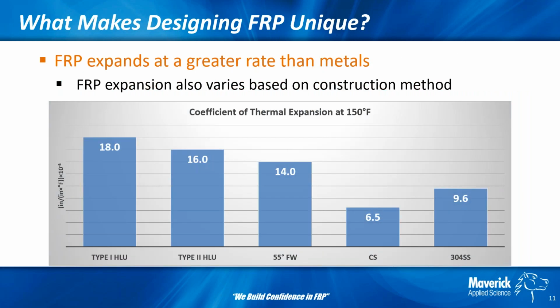Thermal expansion. This is a very big deal for FRP compared with steel. The bar on the left is for type 1. So the resin is what expands, so you'd expect type 1, most resin content, to expand the most. It's important to note here, you have 3 different construction methods and 3 different thermal expansion coefficients. So it's crucial to know which one you are using in your analysis. The main takeaway from this is obviously the coefficient of thermal expansion changes between products for FRP, but also compared to steel. Just looking at carbon steel, you're anywhere about 2 to 3 times that of what steel is.